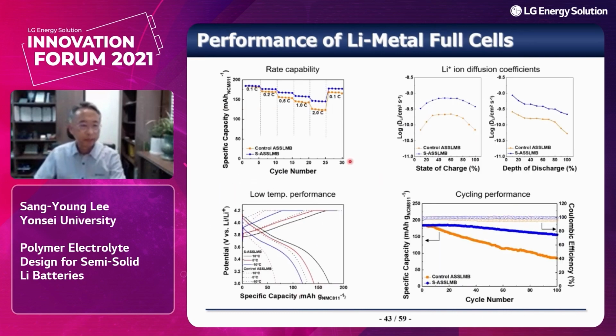Then we investigated the electrochemical performance of the lithium metal full cell in comparison to the control cell, which contains the pristine polymer electrolyte. Our single ion conducting polymers can provide a higher rate capability, which was verified by the faster diffusion coefficient of lithium over a wide range of state of charge and DOD. An interesting point is that the single ion conducting polymer also improves the low temperature performance due to the suppressed polarization effect.